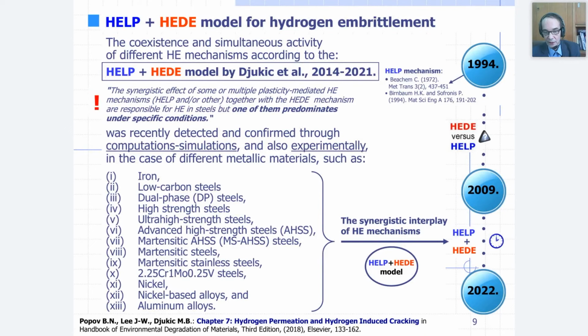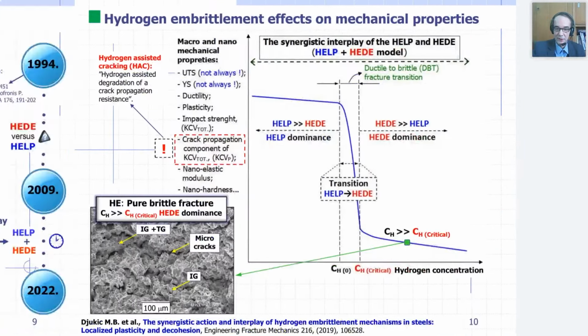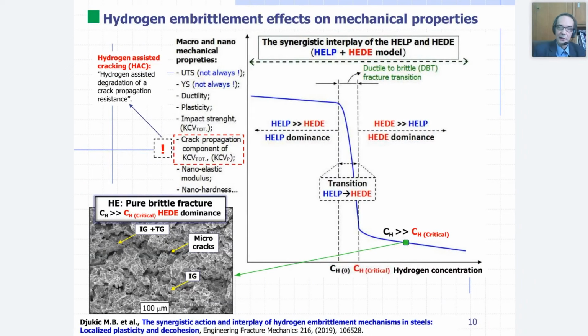So the synergistic interplay of hydrogen embrittlement mechanisms tells us that some of multiple plasticity-mediated hydrogen embrittlement mechanisms, HELP or other, together with HEDE, are responsible for hydrogen embrittlement, but one of them is predominant under the specific condition. So as the summary about the mechanical properties according to our HELP HEDE model, you can see here that we have a critical hydrogen concentration on x-axis, and we have two cases, the actual hydrogen concentration below or above the critical hydrogen concentration. So as you can see, at reaching the critical hydrogen concentration, we have a ductile to brittle fracture transition and sharp drop of some of micro and nanomechanical properties.